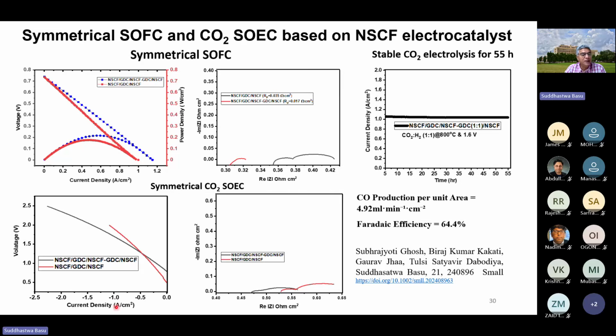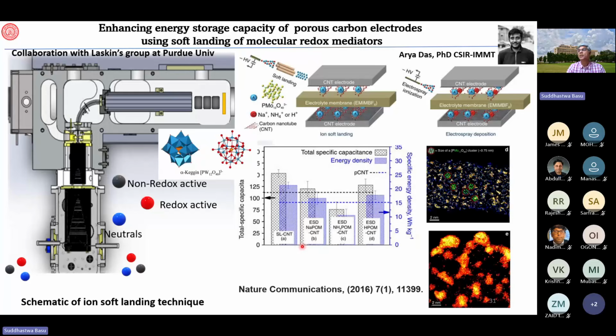When we see the SOEC performance, we got a current as close as about 1 ampere per centimeter square. And it shows that when you have a functional layer with NSCF, we have less polarization resistance. So every way it is making sense. And time is up. I had a topic on ion soft landing.